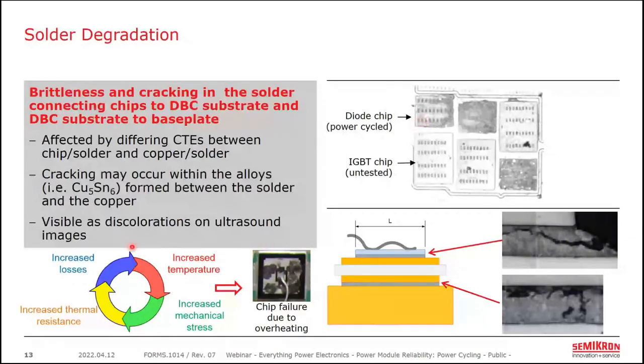Of course, this degradation process can be looked at as cyclical as well, with the electrical resistance from the chip down to the DBC increasing. But in the case of the base plate solder, it is the thermal resistance instead of the electrical resistance to the plate that's increasing. So in certain devices, that can be accelerated by electrical characteristics that increase losses at higher temperature. But most simply, higher thermal resistance means higher temperature differentials and higher CTE induced stress. And again, the end result is the destruction of the chip.